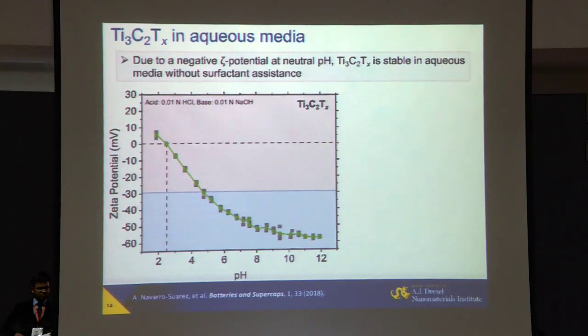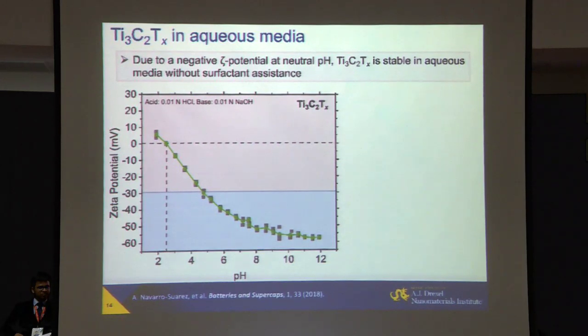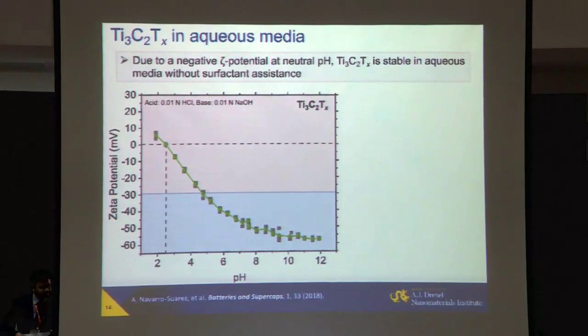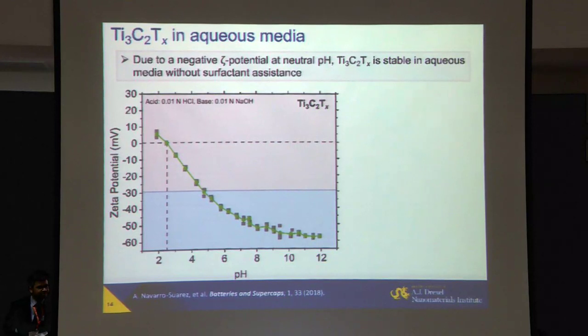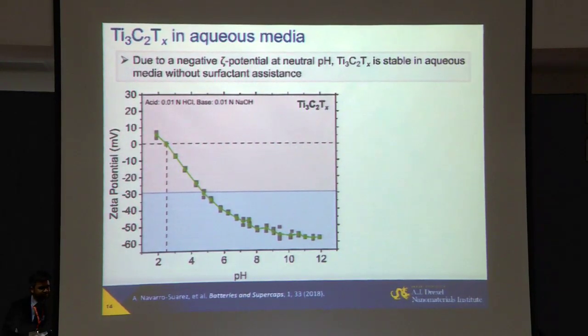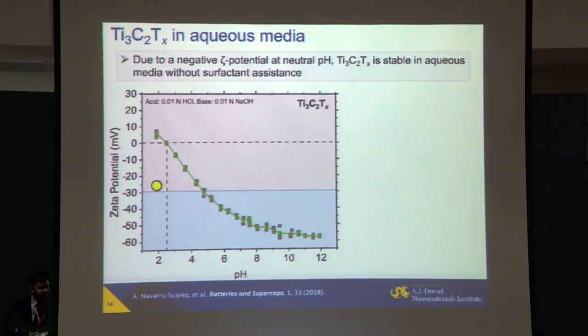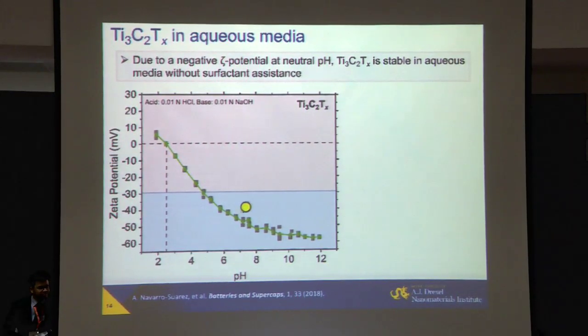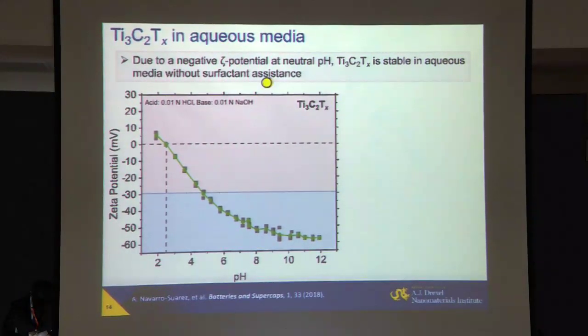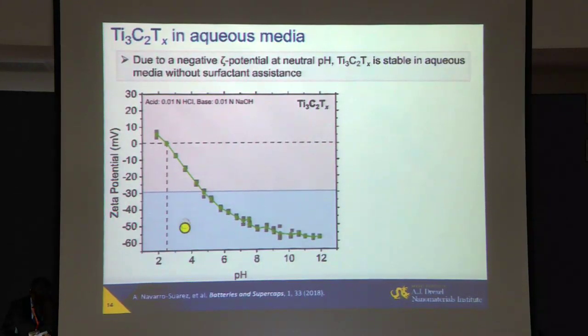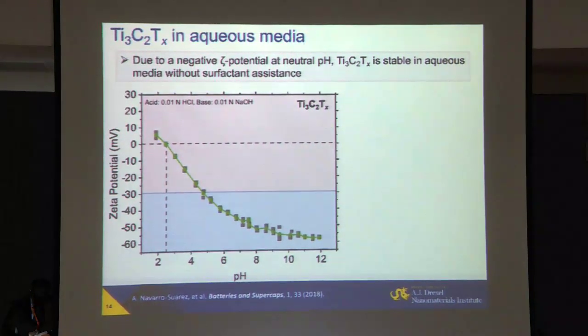Moreover, what is also very useful in the majority of applications is that we don't need toxic solvents to disperse them, because unlike hydrophobic graphite or graphene, they can be dissolved just in water. Because, going back to your chemistry background, if there is a zeta potential which is below roughly minus 30 millivolt or above plus 30, the material forms a stable colloidal solution. So you see at near neutral pH, MXene will, and this is titanium carbide Ti3C2 example, form a nice colloidal solution.